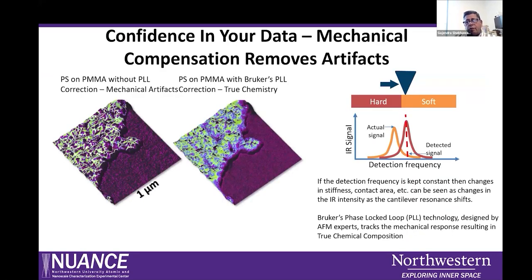And then in the AFM, there's always an issue when any oscillating probe interacts with the sample. Depending on the density variation of the sample, there's a shift in the frequency. The shift in the frequency can be more for softer materials compared to harder materials. So how do we know that whatever variation in the IR imaging we are getting is a true sample interaction, not from other mechanical variations like stiffness or contact area?